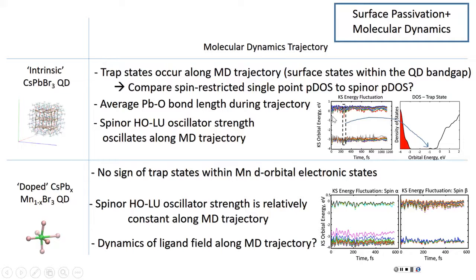So, yeah, these fluctuation charts show that along the trajectory there are states that go lower than where the orbital started out, and those are usually indications of trap states. Well, for me, they'd be indications of trap states that occurred during the trajectory. To illustrate the point more clearly, I took a time step, illustrated around this black box. I took the position file from there and just did a single point calculation. You can see that there's a little hump inside the gap.